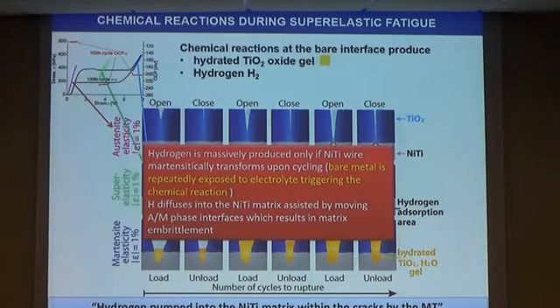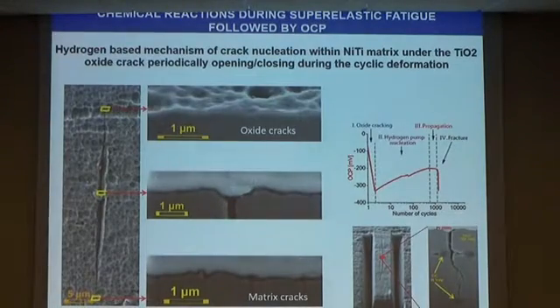The problem is that hydrogen is massively produced if the wire transforms martensitically. The bare metal comes into contact, and the hydrogen diffuses into the matrix, which we believe is assisted by moving phase interfaces. So it's like a hydrogen pump, here without any hydrogen atmosphere or any electrolytic charging. You still have generation of hydrogen. To prove that, we should find the correspondence between the oxide cracks and matrix cracks. It was very difficult, we tried, but finally we managed.